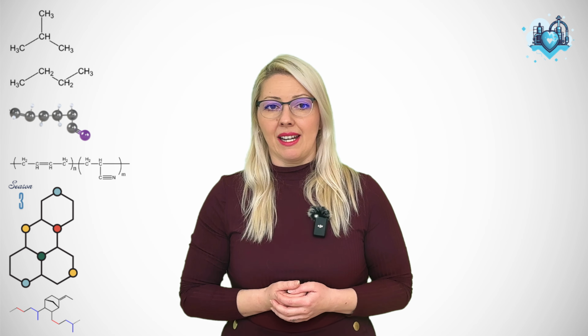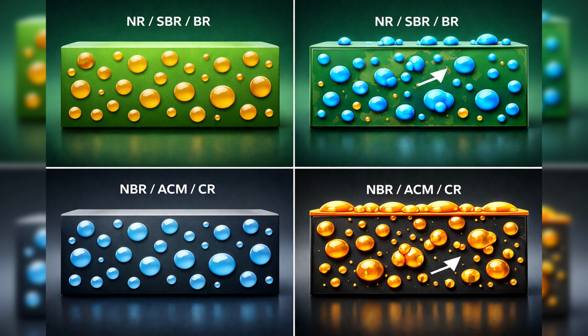Oil migration depends strongly on how chemically similar the oil is to the polymer. Oils prefer environments that feel chemically familiar. When compatibility is good, the oil dissolves into the polymer phase and its chemical potential stays low. When compatibility is poor, the oil is only partially soluble and wants to escape. In non-polar rubbers like NR, SBR, and BR, non-polar oils like paraffinic or naphthenic oils are usually stable. In polar rubbers like NBR, ACM, or CR, polar oils are much more compatible.